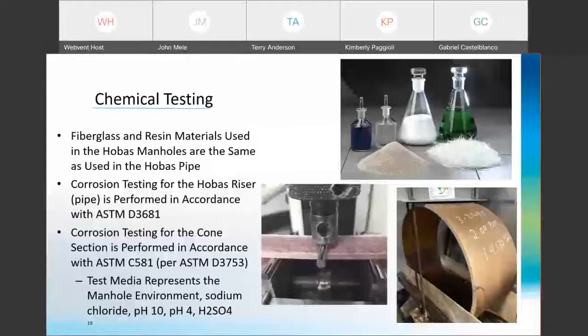Additionally, corrosion testing per C581 is performed on specimens taken from sheet laminates made of the same composition as the manhole cone. Several test media are chosen to ensure long-term performance in a wide variety of chemicals.